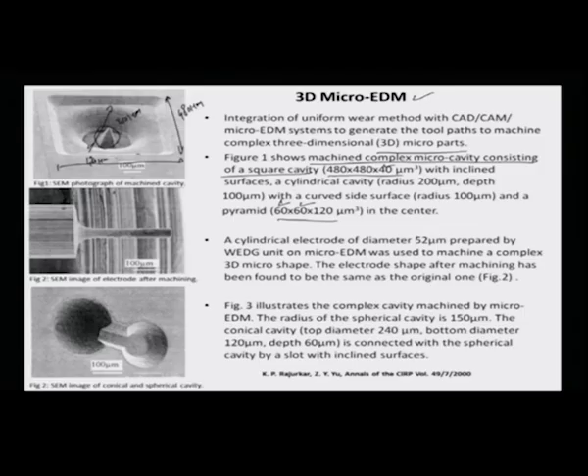Figure 2 again is a circular electrode, the SEM image of a circular electrode, and this tip size here must be close to about probably tens of microns. So, this is doable again using a micro EDM process. And this cylindrical electrode was prepared by a wire assisted electro discharge grinding unit, and I think I had illustrated earlier that with another kind of an identical wire assisted process, we had produced about 2 microns of tip size. In this particular case, although the tip size is slightly higher, about 52 micrometers, it still is a very high improvement over the other machining processes which exist.